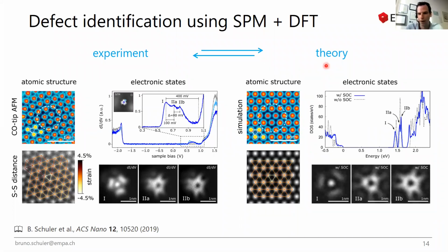And then we try to make an educated guess what these things might be. We perform ab initio theory, and by we, I also mean collaborators of ours, especially Xunho in the group of Jeffrey Neaton in Berkeley. It's very helpful in doing so. And then we can compare, and we see all the evidence we have and try to see whether we have a good match or not. And usually if it's not a good match, it's very clear. For instance, the electronic states are completely different. The spatial, kind of orbital shape doesn't match and so on. So when we have this really full agreement, we can be extremely confident that the assignment is actually correct.